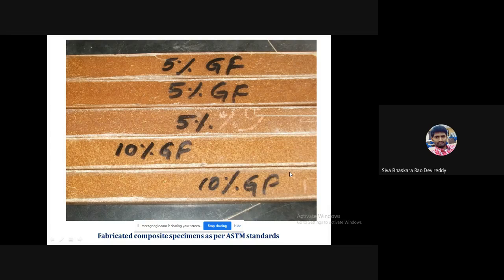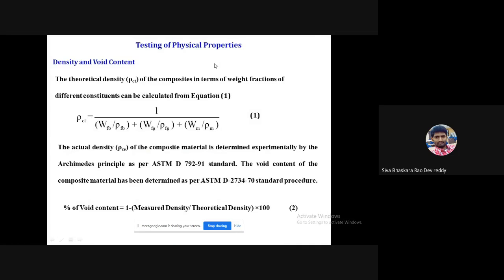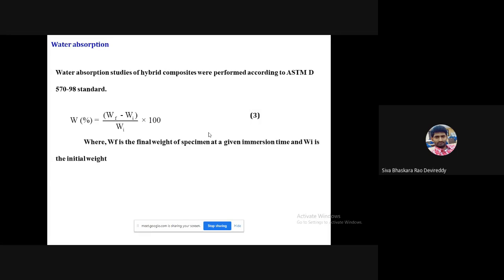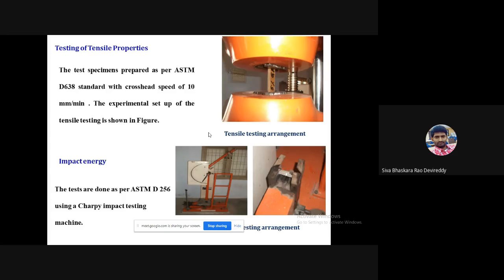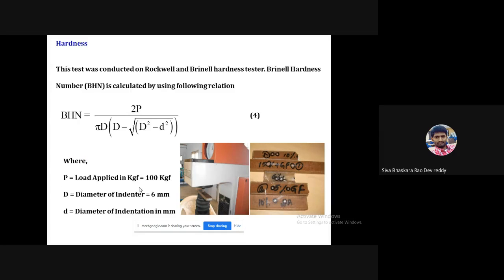These are the fabricated composites with different percentages of broom grass root and glass fiber. Next, coming to characterization, density and void content were calculated. The theoretical density was calculated by this equation 1, written by Agarwal and Broutman, and the experimental density is calculated by the Archimedes principle. The water absorption of the composites was performed as per the ASTM standard. The difference between the specimen's weight before immersion and after immersion was taken and calculated by using this formula. Tensile test was conducted on a UTM with ASTM standard D638, and impact energy is measured on a Charpy impact tester with ASTM D256. Hardness was measured by using this Brinell hardness tester with this formula.